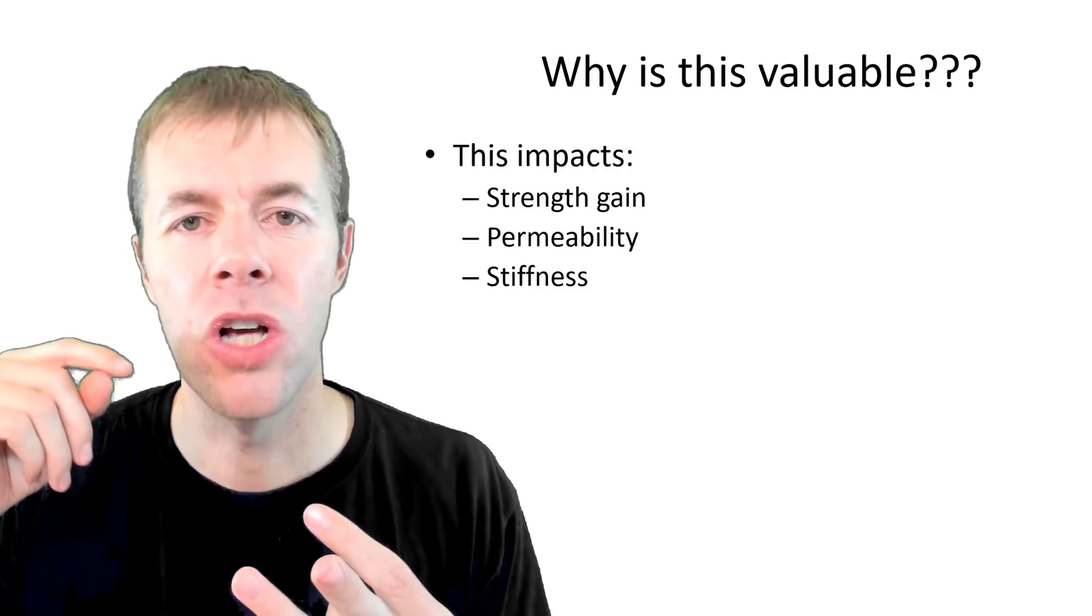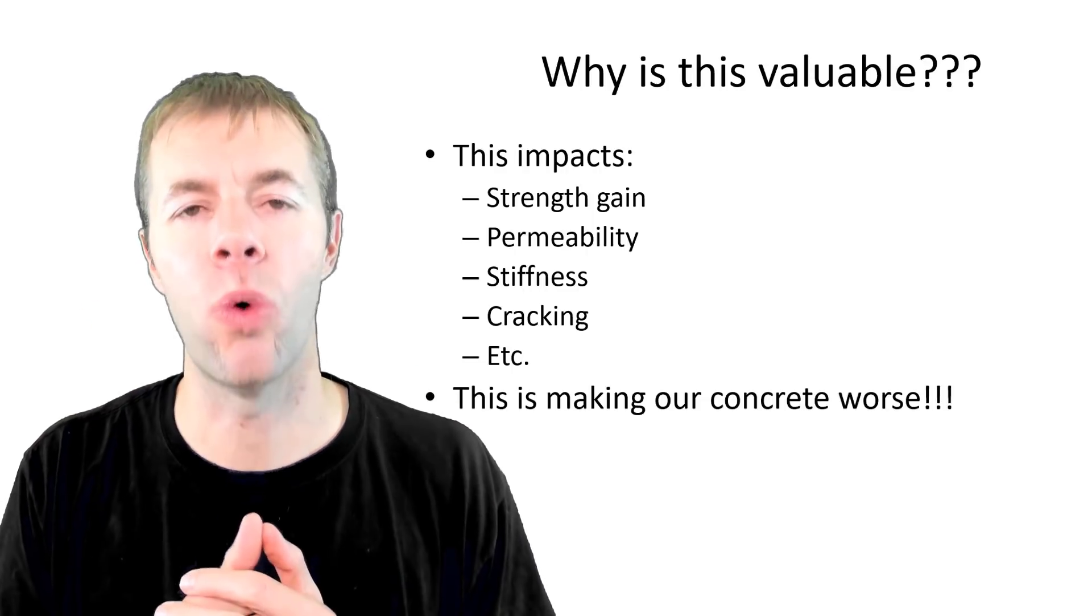So why is this valuable? This impacts your strength gain, your permeability, your stiffness, your cracking, so many properties of concrete. This porosity formation is making our concrete worse. If we could find a way with admixtures or some other procedure to stop this, we could make a huge improvement in our concrete. Again, look at this six hours to nine hours. We don't want to lose all this hydration product that we've worked so hard to make. We want to keep it in place.